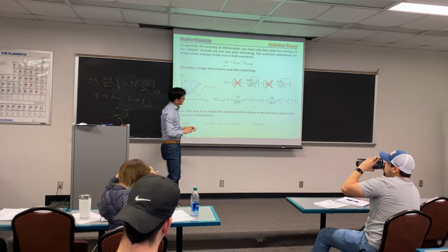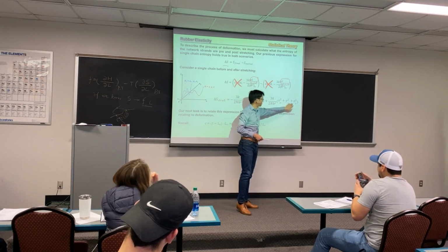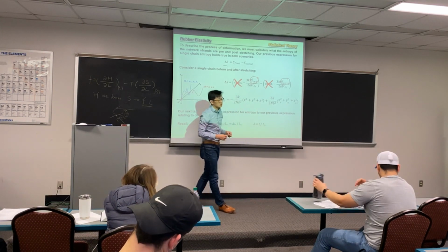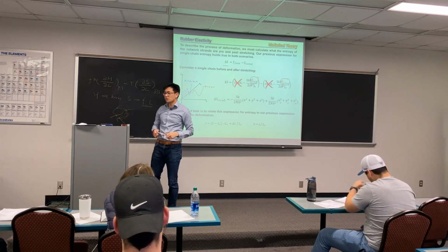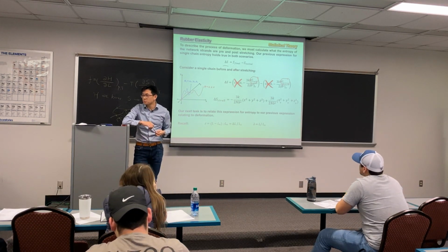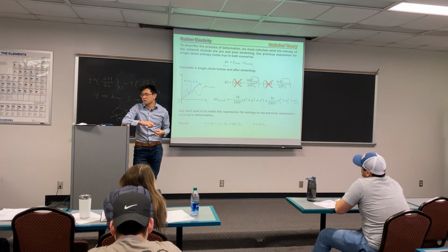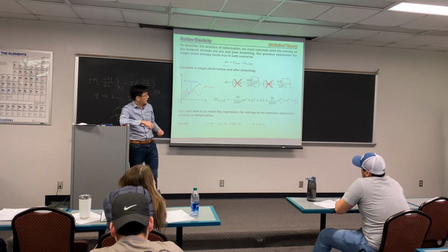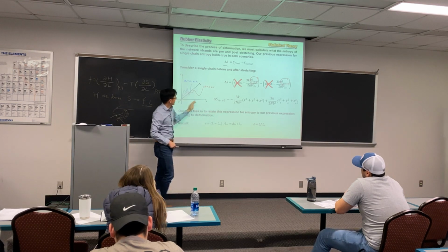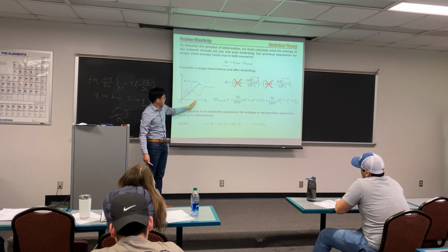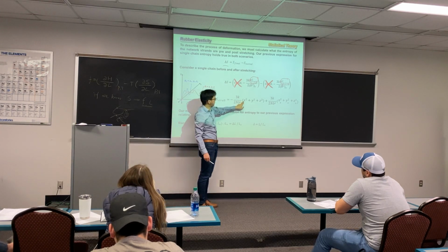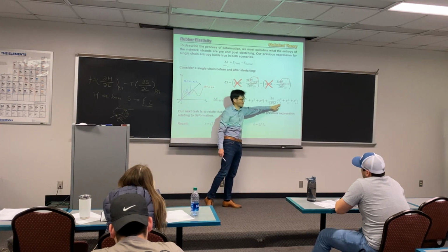If we know these two are linked, as well as the z position, then we should be able to resolve what the entropy change is before and after we stretch, right? That's the only thing we're missing here. X is already defined because we assume the sample is stretched in the x direction, and x will just be equal to lambda multiplied by x0.